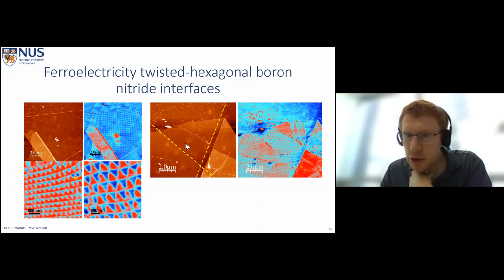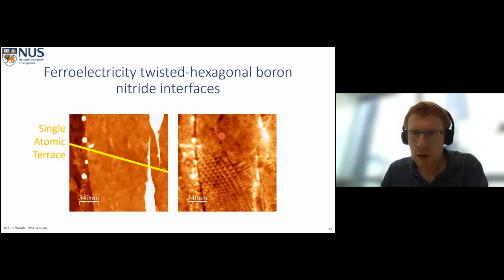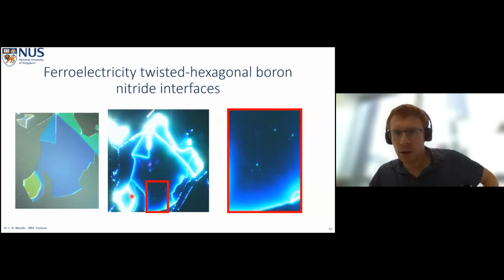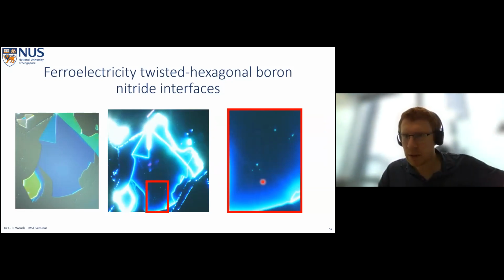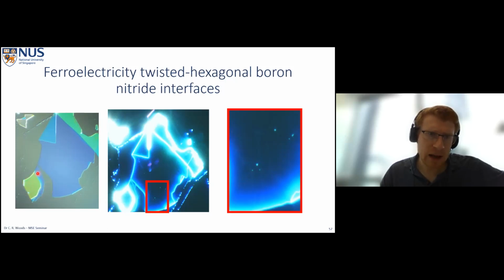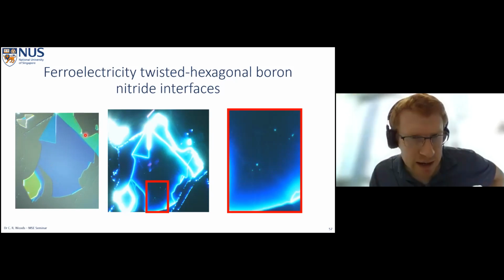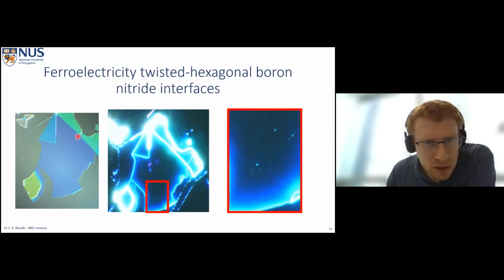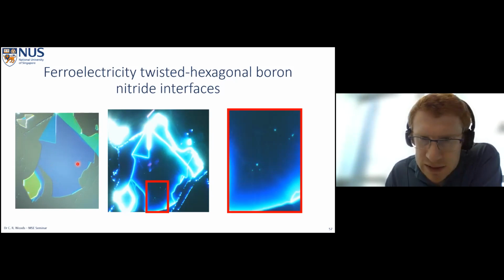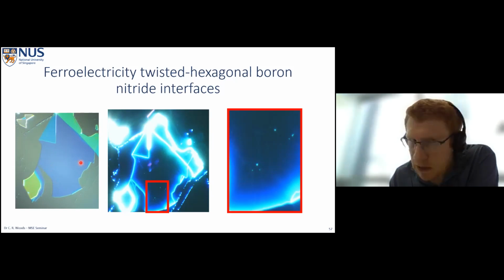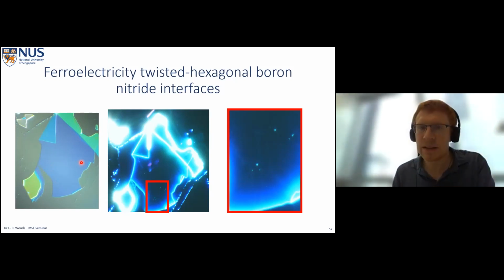So how do we introduce the twist between boron nitride with such control? So that's a fabrication technique. It's a good question. Let's go back and look at our sample. I showed you this picture because I think it's interesting for people to know that these monolayer terraces and stuff are possible to see, but they're very difficult. But if we look at this image on the left, this is just a boron nitride flake. And what we can see is that it has some very straight edges. At the top here, these edges are very straight, almost suspiciously straight. And actually this is because these materials, when you mechanically exfoliate them, tend to crack along the zigzag and armchair directions.